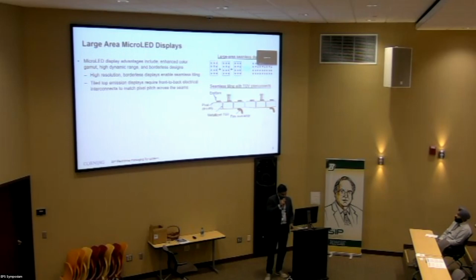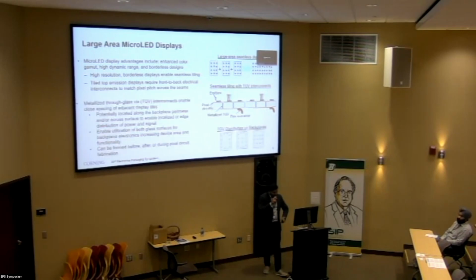And also, another issue is that routing the electrical signals becomes more complex because now it becomes a bigger display. So one way to do that is you can seamlessly tile these smaller displays to make a big display. At the same time, you can drive the interconnects for connecting the emitters on the TFT backplane on the A side to the IC driver board on the B side using the through glass vias. So these through glass vias can be located along the perimeter of the substrate or perimeter of the tile, or they can be distributed across the pixel circuit for driving the power signal.